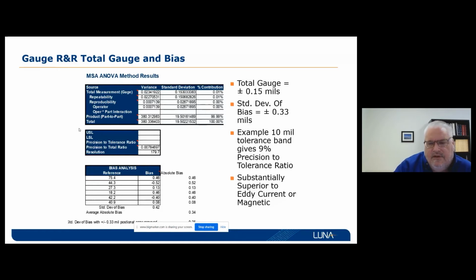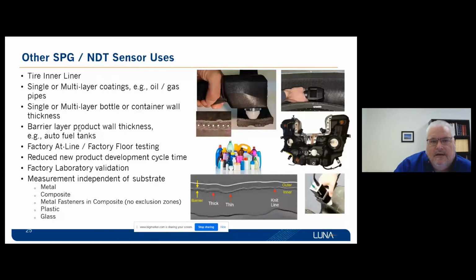And so this has very low bias and is substantially superior to eddy current magnetic gauges. In head-to-head measurements, the terahertz would often have 40 to 100 times better precision to tolerance ratios. So many of the legacy gauges were just simply inadequate for these measurements. Other kinds of handheld sensor uses here include measurements of tire layer thicknesses, inside of blow molded parts, bottles, etc.